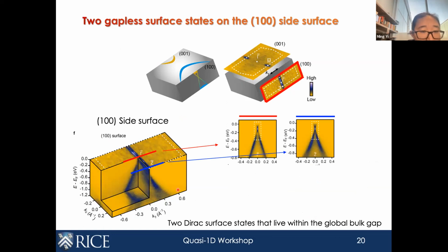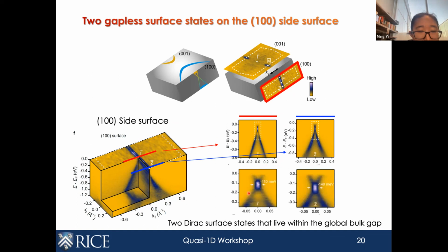Okay, next, let's look at the side surface. The side surface here, we can see that, again, at the gamma point, also at the Z point, there are very clear Dirac crossings. And if we zoom in, we can make out exactly the energy where the Dirac crossing occurs, 110 millielectronvolts, 140 millielectronvolts below the Fermi level. Now, what's interesting is that these two Dirac points, not only do they live within the bulk gap of the 100 side surface, but they also live within the bulk gap of the top 001 surface. That means that in this energy window, there are no other bulk states anywhere in the crystal, and all that's left are these topological surface states, the two Dirac cones, a very clean and simple electronic structure.